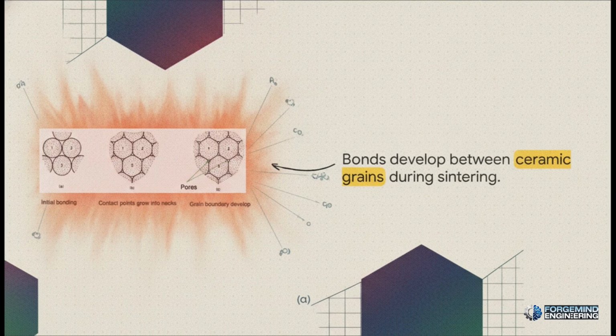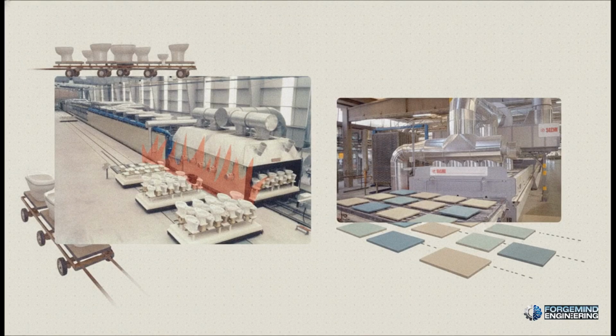We aren't melting the ceramic into a liquid pool. Instead, the intense heat causes the individual ceramic grains to actually bond together at the atomic level. See how those initial contact points physically grow into solid necks, eventually forming a dense network? That thermal forging is what drastically increases the material's strength. Now zooming back out to the macro scale, this sintering happens in massive industrial furnaces called kilns.